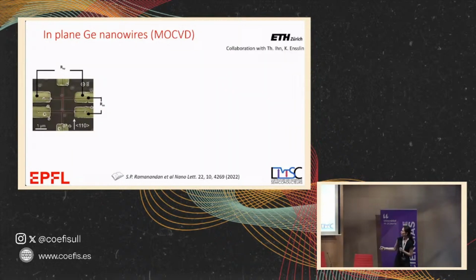What we did is we created Hall bars. So a Hall bar is where you have a single wire, and you make some legs, some arms, so that then you can measure the potential also in these arms. And you measure the current that flows here, and you apply a magnetic field. And as you know, because of the Lorentz force, when you apply a magnetic field, an electron going here will go on one side or the other, depending on whether it's a positive or a negative charge. And this allows you to measure first what kind of charge there is, but also the mobility, and so characterize if you have coherent transport or not.